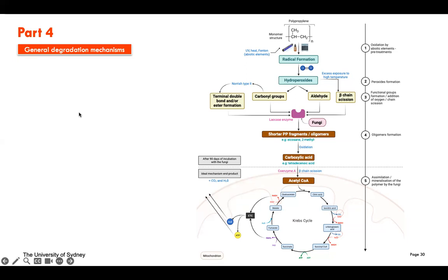So basically this illustrates the pre-treatment process, what has been done, what happened to the polymer during the pre-treatment process, and what happened during fungal action. This overall reaction occurs in the presence of oxygen. Okay, we didn't do any abiotic degradation. So it leads to the formation of radicals and hydroperoxides. And the oxidation of the polypropylene chain results in the formation of carbonyl groups, including aldehydes and ketones, the ones that we found during GCMS before.